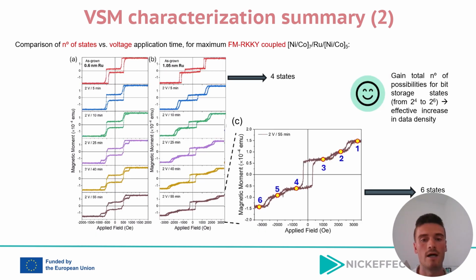A similar comparative VSM study was carried out, in this case of ferromagnetically RKKY coupled structures. Different ruthenium thicknesses were chosen, and the main observation was the increase in the number of magnetic states of the hysteresis loop after successive voltage application time steps. For a ruthenium thickness of 1.05 nanometers, the number of discrete magnetic states increased from an initial 4 to a final 6.